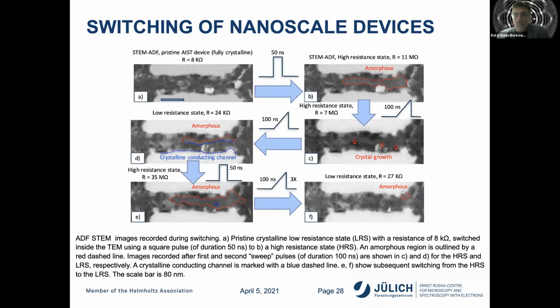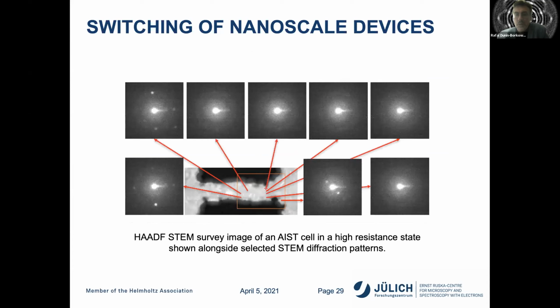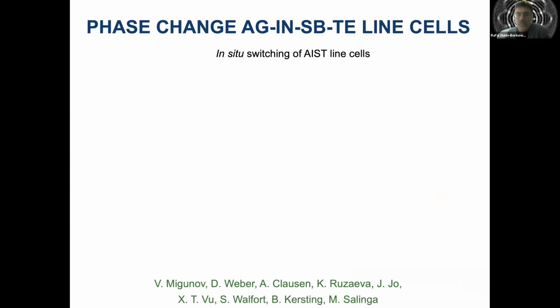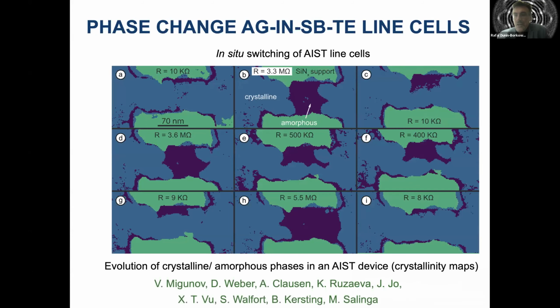So on the one hand, we can take images of the device switching between amorphous and crystalline states subjected to nanosecond pulses. And here we have different images where you can just about see which region is amorphous and which region is crystalline. But it's much better, instead of forming images like this, to take diffraction patterns point by point. And here are examples of diffraction patterns taken as a focus probe is stepped across the field of view. If we take diffraction patterns point by point, then first of all, we can make a direct map of which regions are crystalline and which regions are amorphous. In these images, everything which is green is a silicon nitride support, everything which is light blue is crystalline material, everything which is dark blue is amorphous.